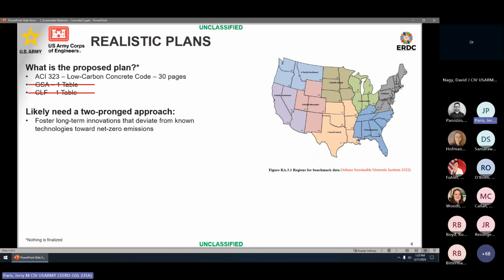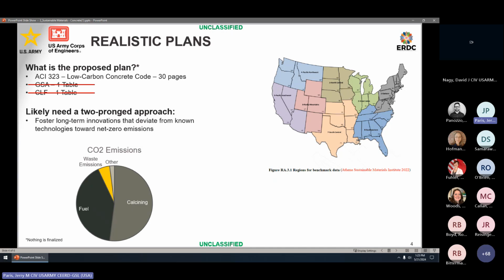And what I mean by that is, and this is my opinion, is that the current process by which cement is produced, I don't foresee that process being net zero, because if we look at the emissions as a function of Portland cement production, over half of it is coming from a calcination process, where what you end up doing is you take limestone and you heat it up until you drive off the CO2, and you're left with reactive calcium oxide. And that's what that portion is. So if we were to have zero emission fuels and waste emissions today, we would still not be in a net zero process.